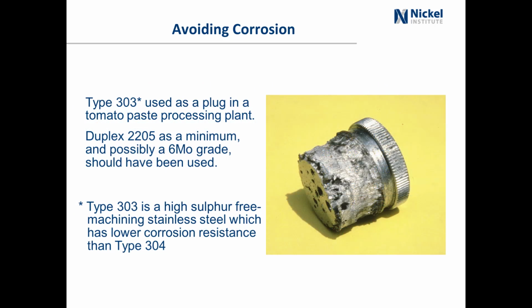Here's a picture of a Type 303 stainless steel used as a plug in a tomato paste processing plant. It doesn't look pretty. And in this case, a duplex or possibly a 6 moly might have been preferred because tomato paste is acidic and has chlorides in it. And part of the reason why 303 didn't work very well is it's a high sulfur free machining stainless steel. So it has a lot of sulfur in it, which reduces the corrosion resistance.